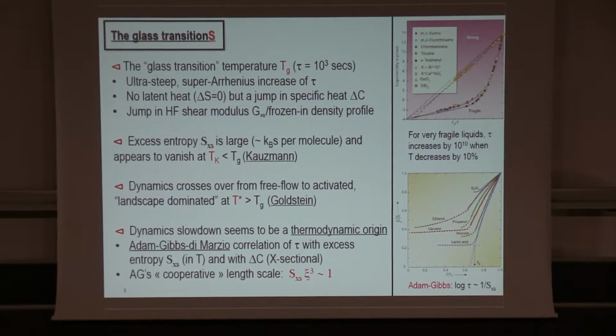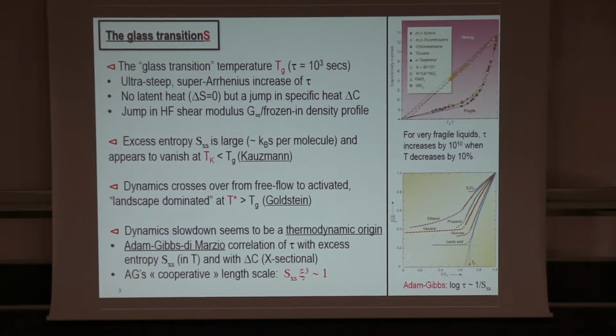And as the glass appears, as it becomes rigid, which is its most important physical property, it does so in a discontinuous way. The high-frequency shear modulus jumps from essentially 0 to a non-zero value as Tg is crossed. The excess entropy of the glass as compared to the solid is large. It's several kBs per molecule. This has been emphasized by Peter, actually.